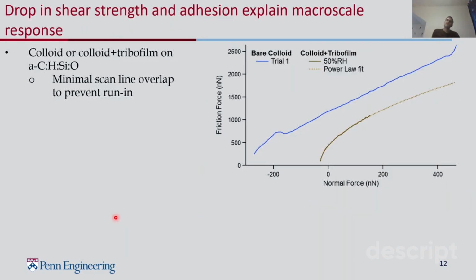We can do an additional set of analysis here. Now that we have a colloid with a tribofilm on top, we can actually measure the friction response of the colloid plus tribofilm case. And so to show this, we have our friction force versus normal force here, and we actually measured the friction force versus normal force in the bare colloid case.